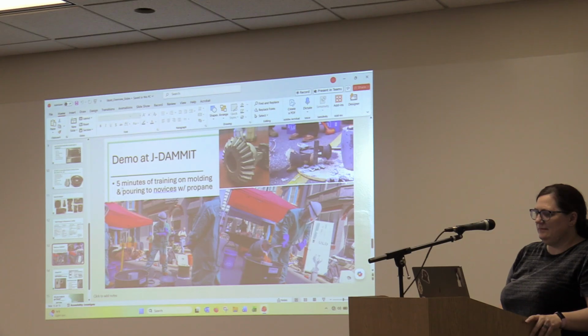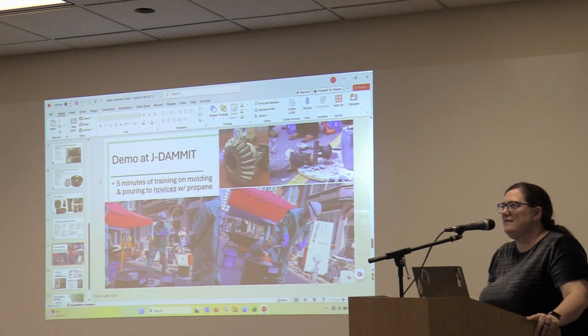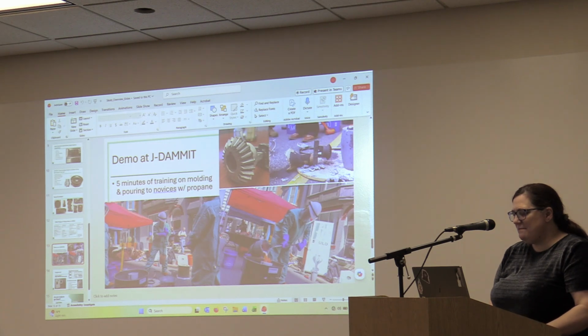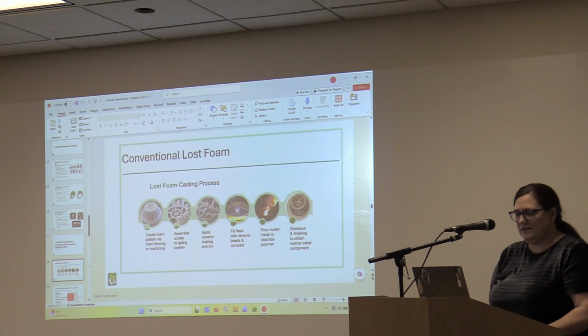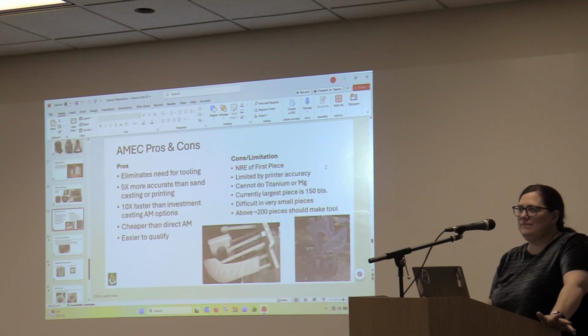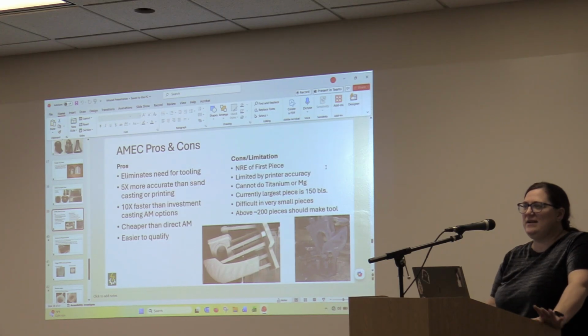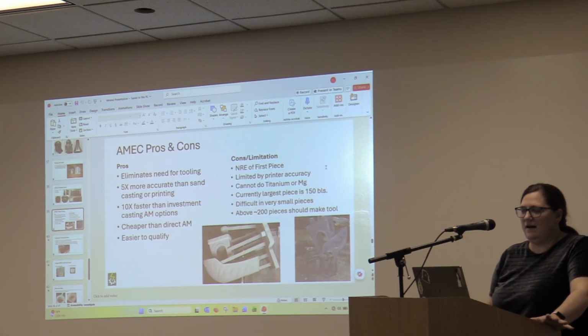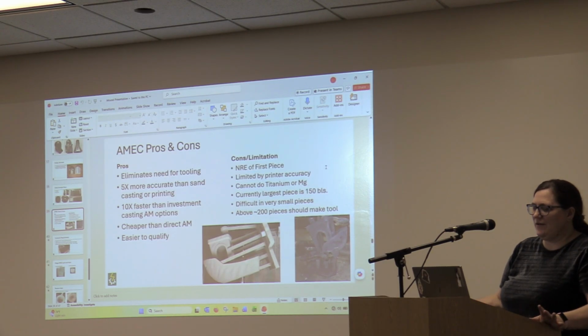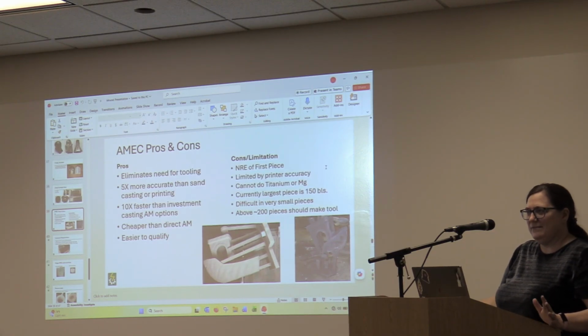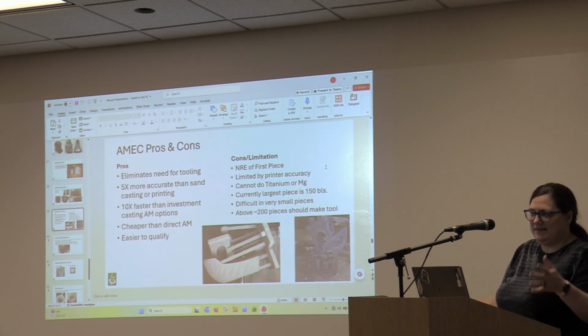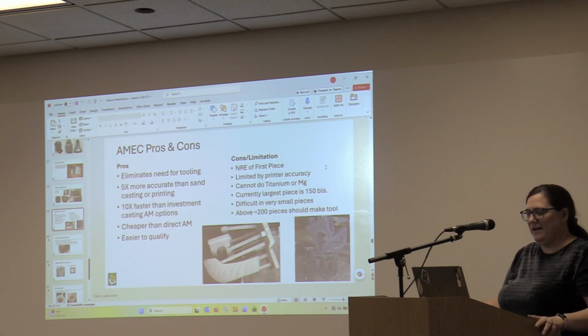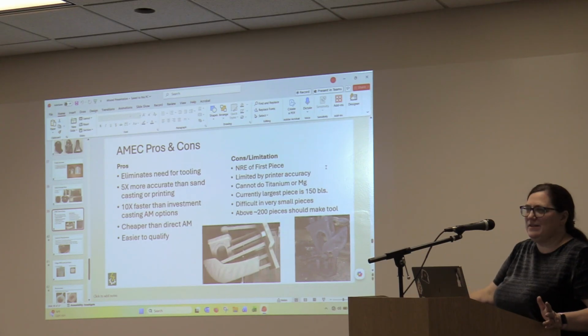So one of the advantages to your company is the ceramic coating. It keeps the detail and keeps the thinness of the shell down. That's one of the things that sets you apart from some of the other processes? I would say the main difference is a couple of things. For us, we also do lost foam, so we tend to use this process as a prototyping method. It's not quite as accurate as regular lost foam, but still far more accurate than sand printing. We think it's about plus or minus 0.5%, whereas sand printing is more like plus or minus 3.5%.